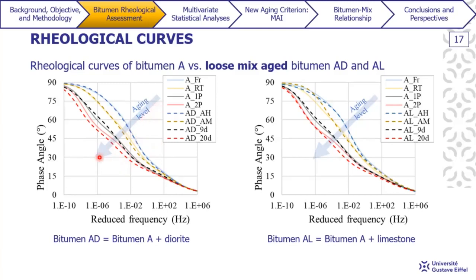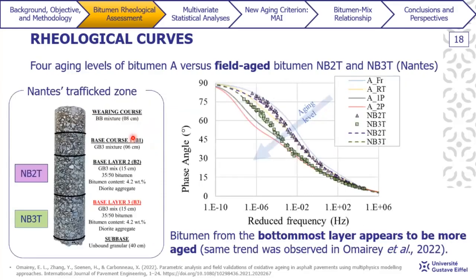So we have the same trend here. We observe that with aging, we have this flattening of the phase angle master curve for both bitumens that were recovered from loose mix aging. And now, the four aging levels of bitumen A versus field aged bitumen NB2T and NB3T from the trafficked zone. NB2T was bitumen taken from this intermediate layer here, whereas NB3T was from the deepest layer of our structure here in the manège.